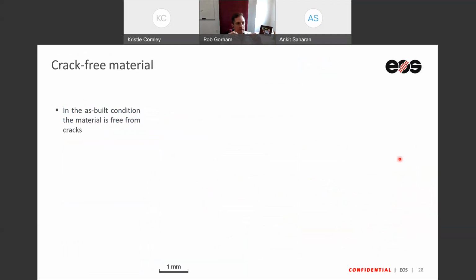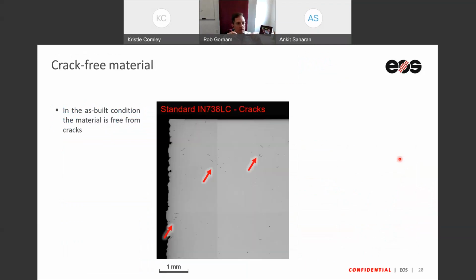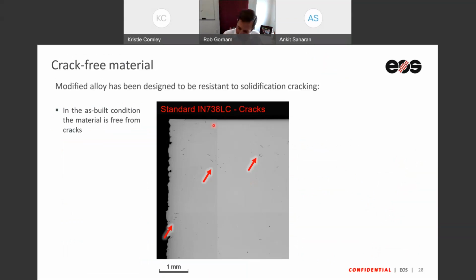So now talking about 738. Now 738, if people know, and if you've actually seen some literature, you can do 738 LC. LC basically is low carbon, but if you can do 738 in an additive environment, no problem. But when you heat treat it, you actually suffer from solidification cracking. And what these solidification cracks are, like you would have this microstructure and you would not be able to see any cracks, but when you do a heat treatment, you would see some of these cracks pop up, and these are solidification cracking that are resulting because of the heat treatment process.